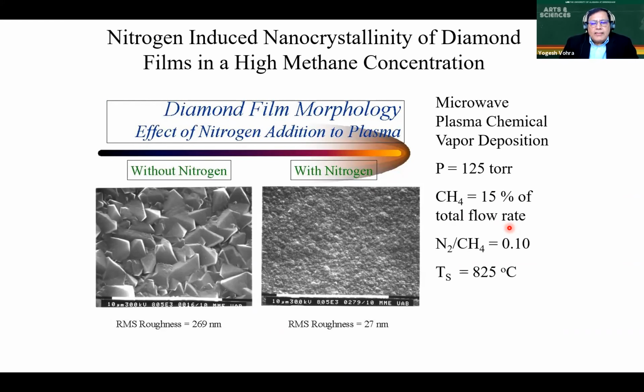And one such example about plasma chemistry is seen in this graph. On the left side, what you are seeing is a polycrystalline diamond film grown with a methane and hydrogen plasma. And the scale bar here is 10 microns. So you see this white bar here. So you can see here that the diamond grain size is about 2 to 3 microns.